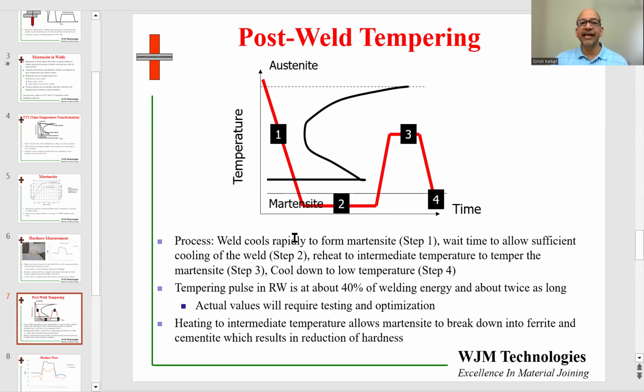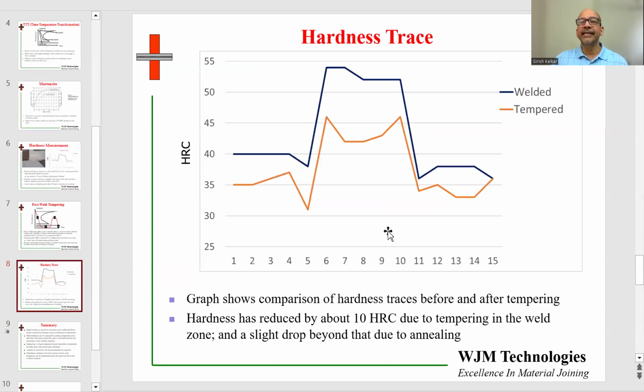So we did a tempering cycle on one of the welds and sent it to the lab. And these are the results that we got. So we see that in the as-welded condition, the hardness was slightly more than 50, say around 52.5. And in the weld zone, after tempering, the hardness has dropped to about 42.5 or 43. So about a 10 HRC drop in hardness in the weld zone.